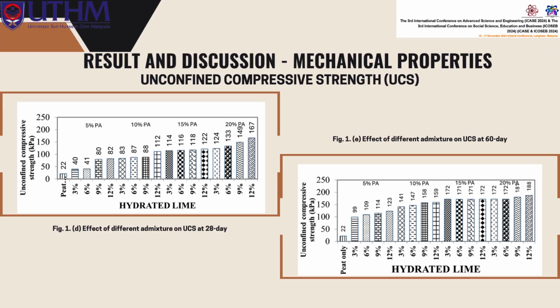The significant increase in strength after soaking the samples for 28 and 60 days, as shown in Figures 1D and 1E, is remarkable. Figure 1D shows a strength increase to 167 kilopascal, 7.6 times that of the untreated sample, while Figure 1E shows an increase to 188 kilopascal, approximately 8.5 times the untreated sample strength. This increase can be attributed to soaking, which enhances hydration in materials like concrete. The soaking process allows water to penetrate the material, completing the hydration of cementitious components, resulting in stronger bonds between aggregates and the cement matrix.